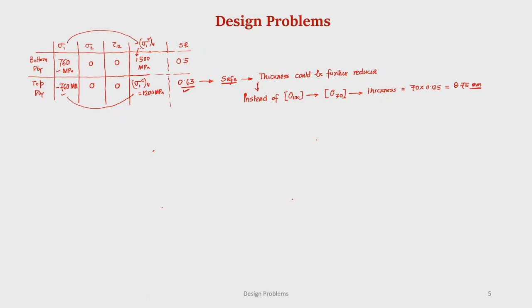Okay. Or else, what we can also do is, instead of reducing the thickness further, say maybe we can use glass epoxy, because glass epoxy, the strength is less compared to graphite epoxy, therefore, thickness will be slightly more compared to graphite epoxy, but then in terms of cost, the cost may be less. Therefore, we will have to take a decision whether we should go with graphite epoxy or glass epoxy. So, there could be number of solutions to this kind of problem, and you will have to really look for the optimum one depending upon different constraint.